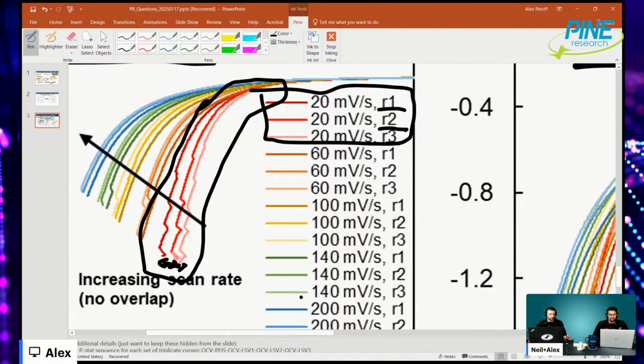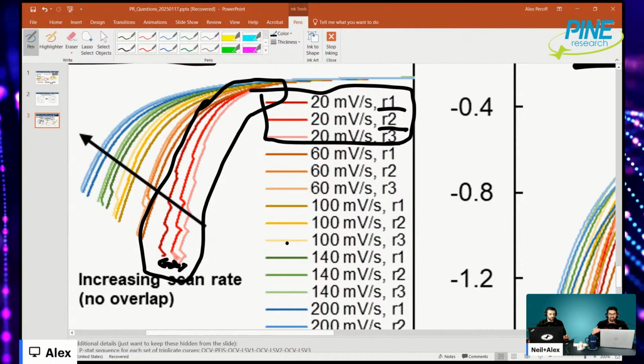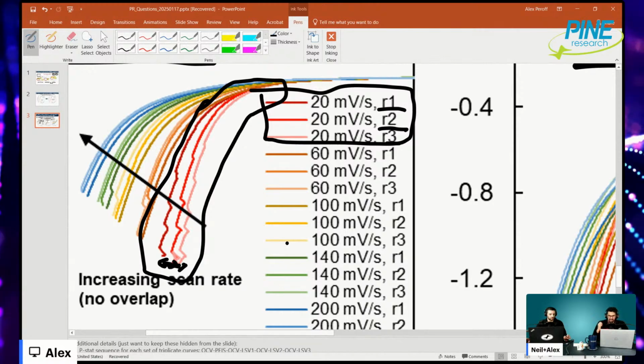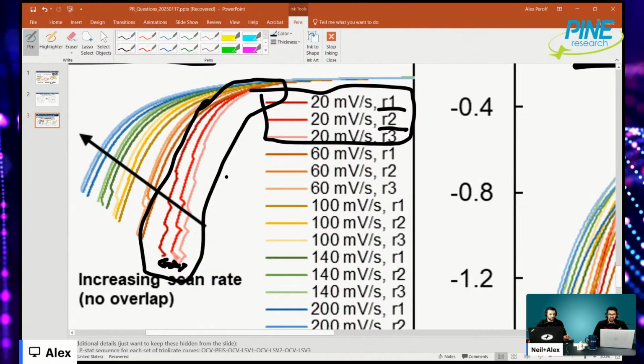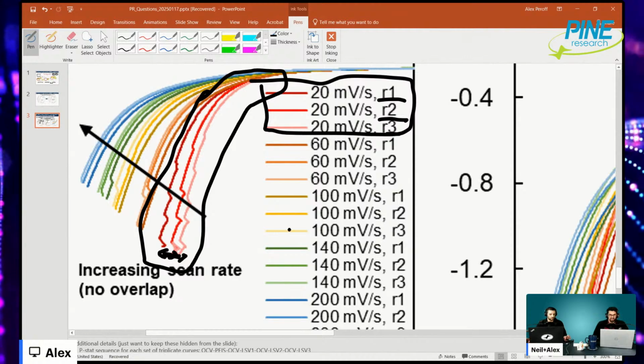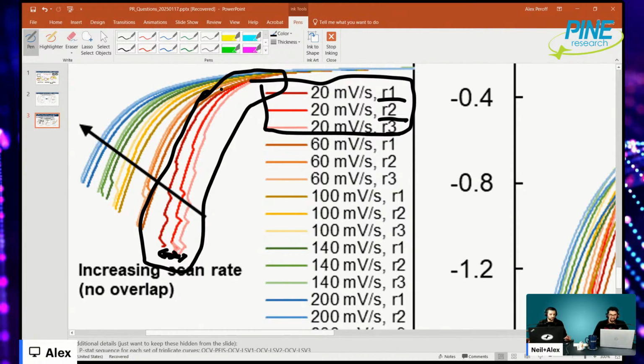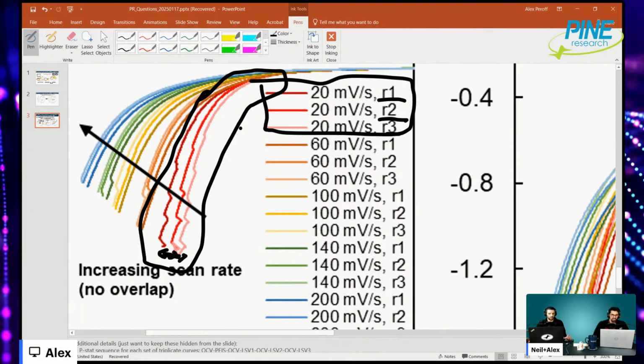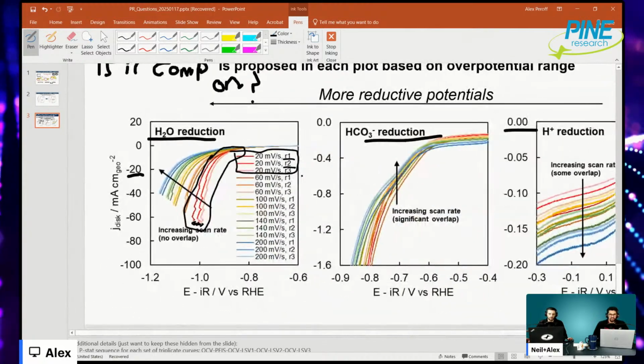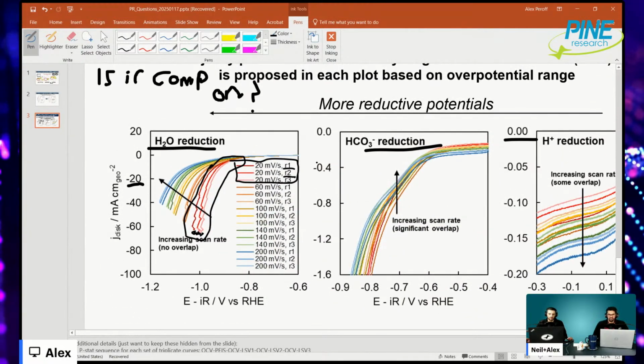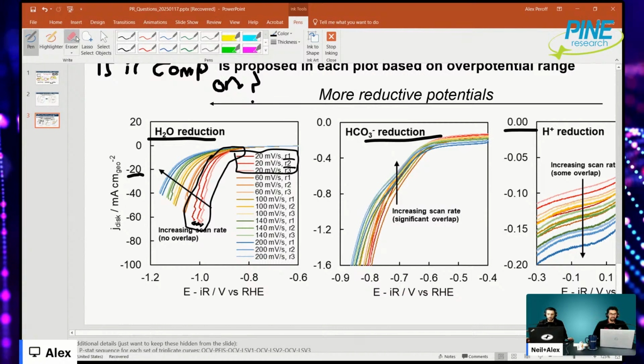And so that leads me to think that IR compensation is not necessarily turned on. I'm not 100% sure, but it's an explanation as to why you're getting this shift: partially because as you move to faster and faster scan rates, you're getting more current. Current times the resistance is also pushing the potential further. That's a hypothesis, without knowing more details. And you did send me some extra data about it, which is very helpful.